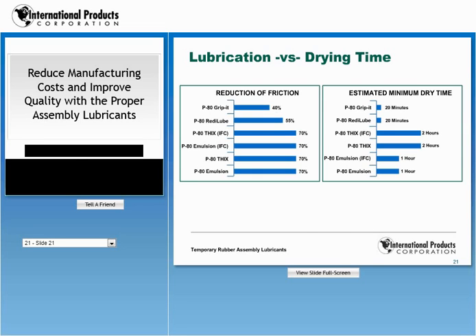There's another way of looking at the data. P80 Grip It reduces friction by 40%, if you see that on the top left chart. And then if you look at the chart on the right, its dry time is only 20 minutes. Going back to the chart on the left, the bottom one, P80 Emulsion, clearly the best lubricant, 70% reduction. It has a dry time of 1 hour. Now everything in between are different variations of the ester technology. Depending on your application, you may choose one over the other.